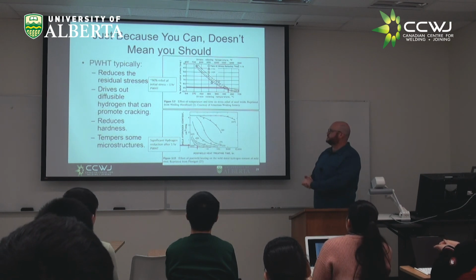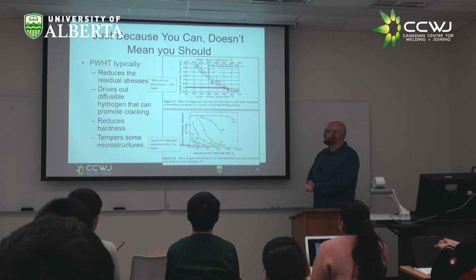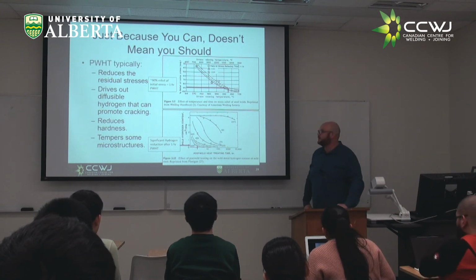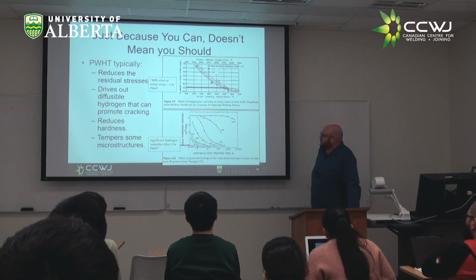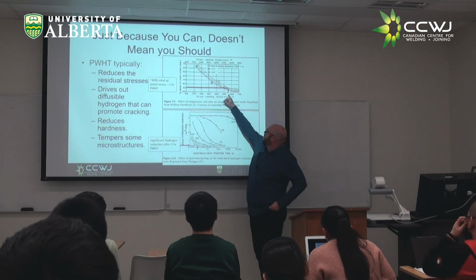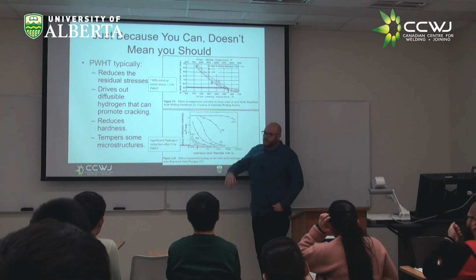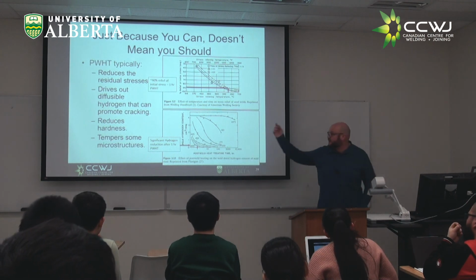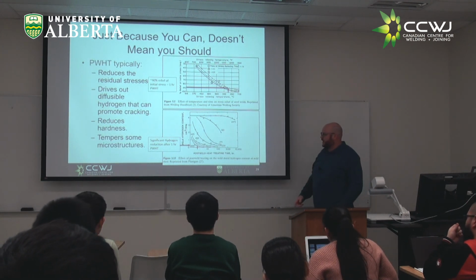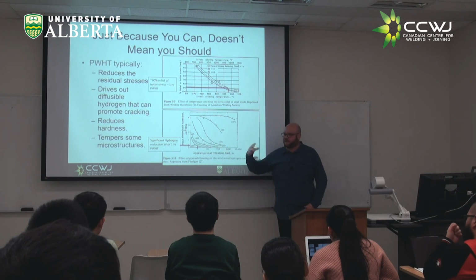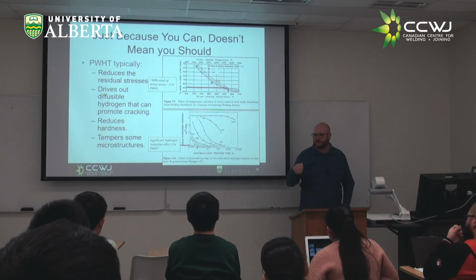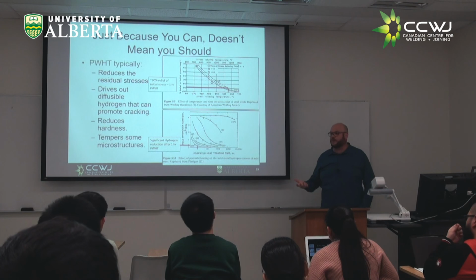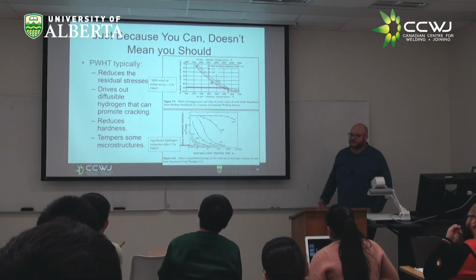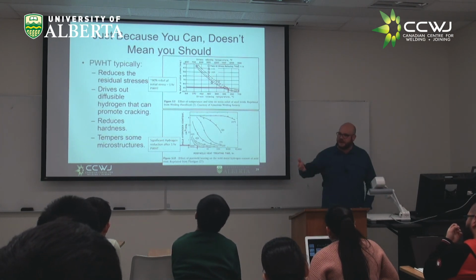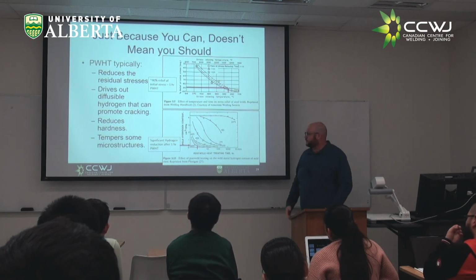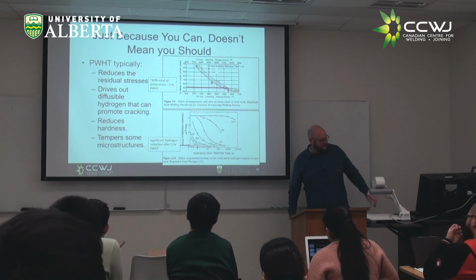So post-weld heat treatment is good for a lot of different reasons. There's a reason why it was sort of the full go-to mandatory thing. It basically reduces the residual stresses. So you can see if you spend about an hour in your post-weld heat treatment range, depending on your thickness, you can get a 90% reduction in stress. It drives out hydrogen, allows it to diffuse out, which reduces the likelihood of stress corrosion cracking, SOHIC, a whole bunch of different damage mechanisms. It reduces hardness, which can again allow you to meet NACE or some of these other documents that have hardness controls, and it tempers some of the microstructures.